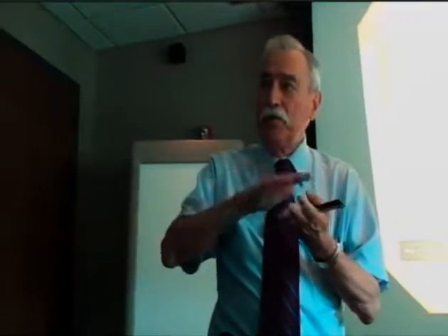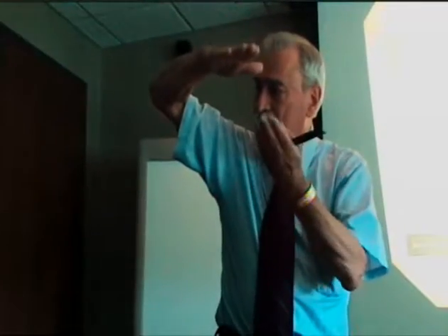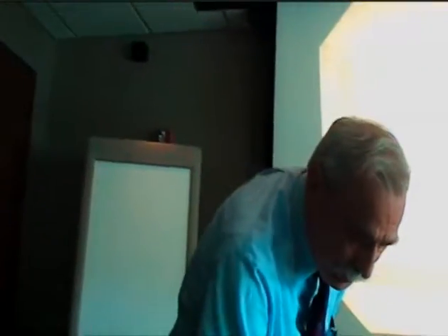So now I look at this and say, let's sulfonate it. Will it fall apart or will it hang together? But we also have made some where we cross-link. And there, now, what we can see is we start to form slabs, not spheres, because in cross-linking, we're holding the layers together to a certain level. We think. You know, all of this is very new to us, okay?